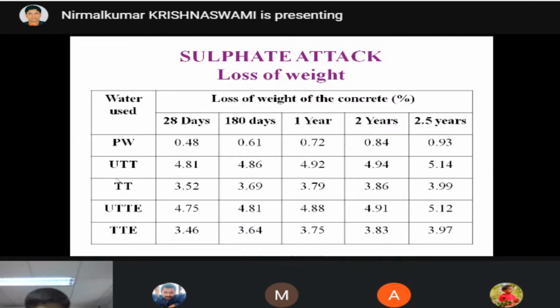Then you see, by using the untreated tannery effluent, the loss of weight is 4.81%. At 180 days, 4.86. At 1 year, 4.92. At 2.5 years, 5.14. See, this is the loss of weight. It is adverse. This should not be the loss of weight, but this is our actual loss of weight.